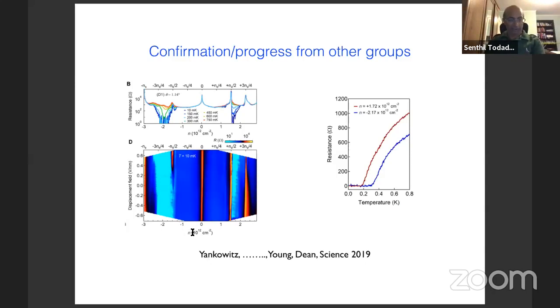So in this plot, for instance, you see that midway between the neutrality and the fully filled insulator, on the hole dope side, at zero displacement field, you see a metallic behavior. But as you increase the displacement field, you enter a regime where you get a correlated insulator. While on the electron dope side, at any displacement field, that's a correlated insulator. Okay, so this was wonderful. Wonderful confirmation, wonderful progress from this paper.